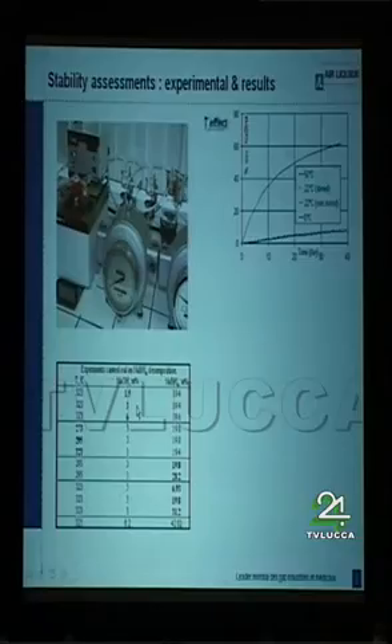The work plan was this one. We made many experiments at 50 degrees with a low concentrated solution of NaBH4, around 20 weight%. And then we made the sodium hydroxide formulation vary from 1.5 to 6 weight%. We made the same experiment but with different temperatures, from 0 degrees up to 50 degrees. We made the concentration of NaBH4 vary too, in order to see the effect, from 7 weight% to 30 weight%. So these are the results.